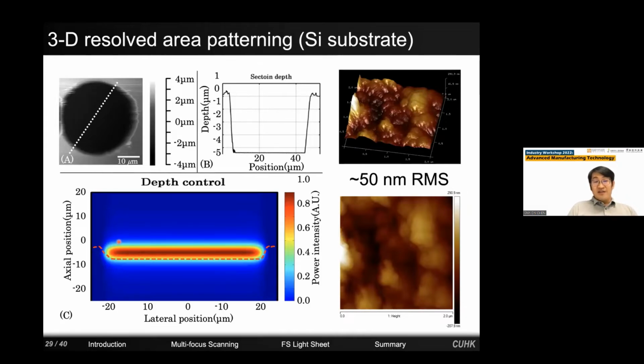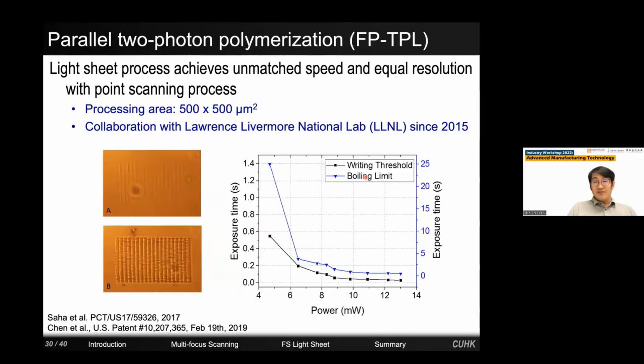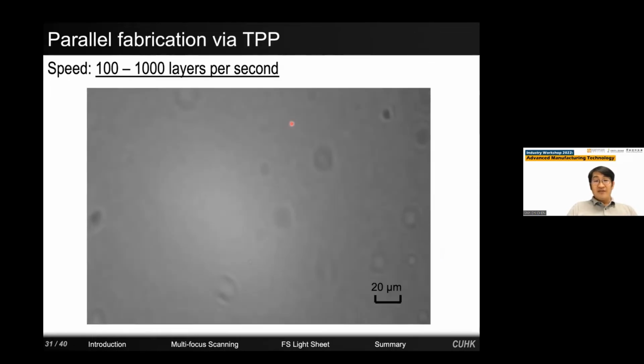You can see it has a thickness around a few microns. It's extremely flat. So by just moving the light sheet around, we can drill flat bottom holes, which reaches a 50 nanometer surface roughness on nickel target. So we apply this to two-photon polymerization in working with Lawrence Livermore National Laboratory since 2015, where they developed custom designed photoresins for us to deal with a high-power laser regenerative amplifier.